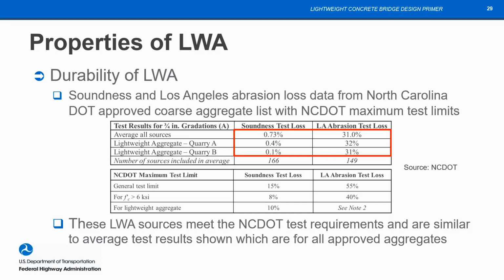What about the durability of lightweight? Lots of us think, can a rock with voids or pores be made a durable concrete? This is some data from North Carolina DOT, picked it up in, I think, 2013 or no, 2020. It has the average for the soundness test and the LA abrasion for all aggregate sources on the list. You can see here 0.73% for soundness, 31% for abrasion. And then there are 2 lightweight aggregates that are manufactured in North Carolina, and they're on this list. Both of them have values for these tests that are essentially equal to or less than the average for all of the ones in North Carolina.